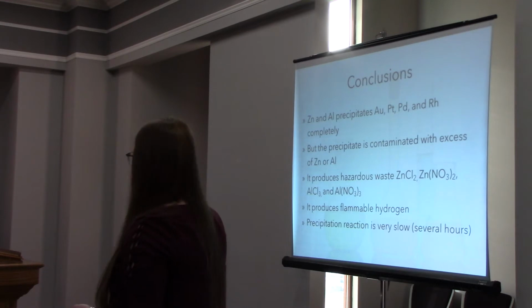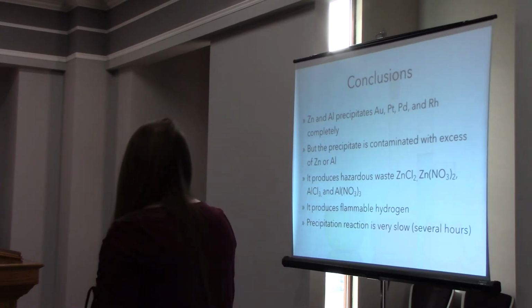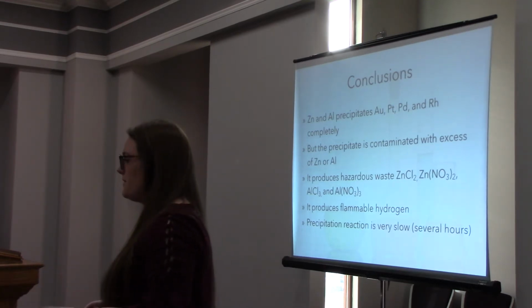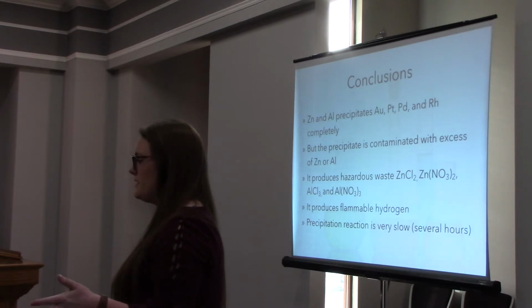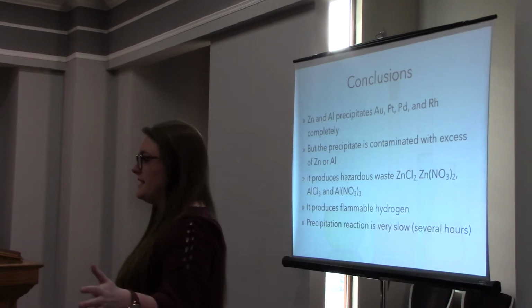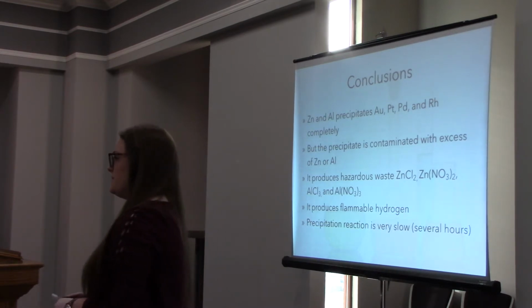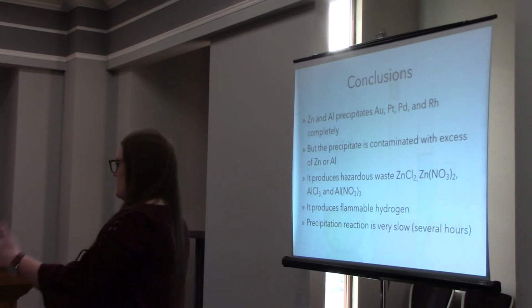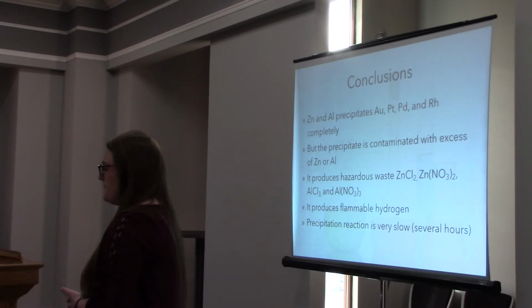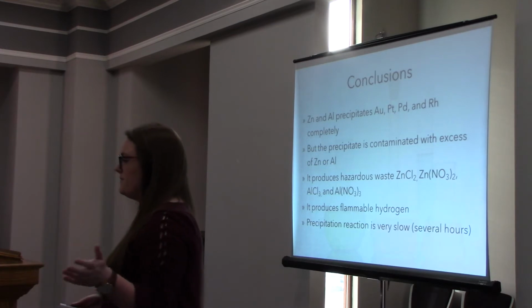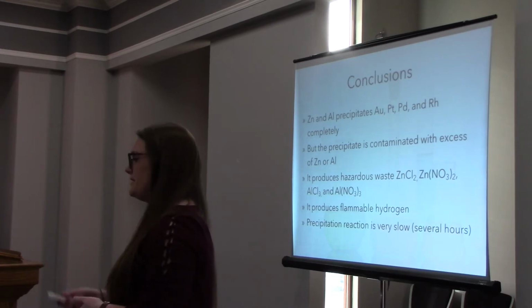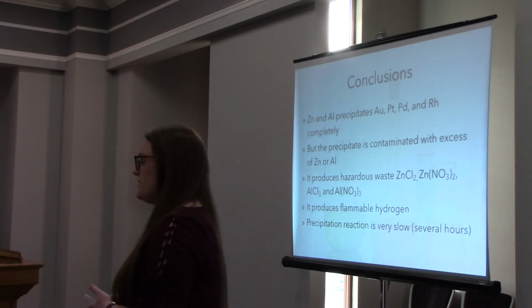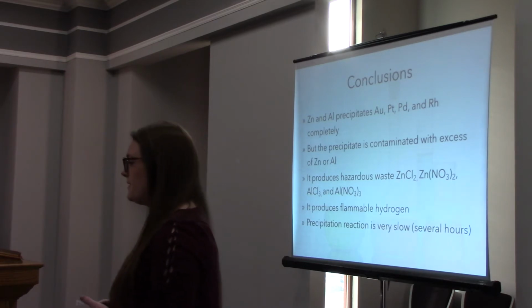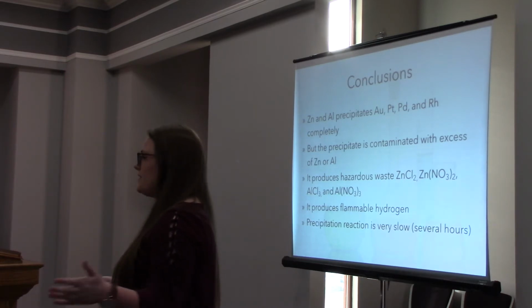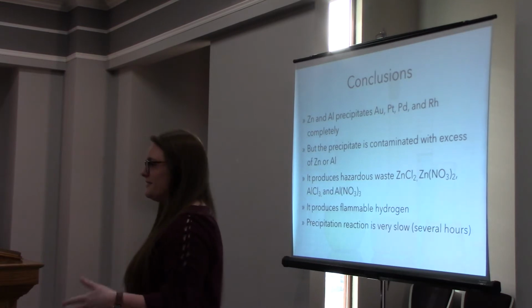The zinc and aluminum will precipitate all gold, platinum, palladium, and rhodium, but this precipitate is then contaminated with an excess of zinc and aluminum because you have to put so much in it in order to get a precipitate. It also produces hazardous waste like zinc chloride and zinc nitrate. It also produces flammable hydrogen. And this reaction takes a really long time, several hours to do.